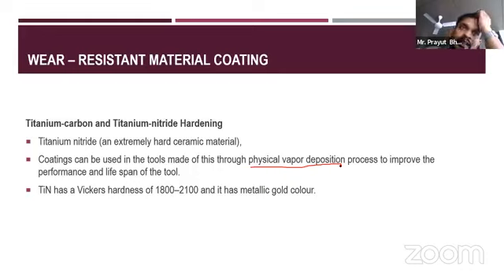So through this process it is done, and it is a costly process. It is basically used for tooling. So basically, on the raw tool, whatever the hardness and properties of the raw tool are, on top of that we do vapor deposition, and this titanium nitride is what we use to deposit on it. And that way, because of this highly ceramic material, the wear resistance also increases, the cutting application also increases, because what we say is the cutting tendency of this material is very high.